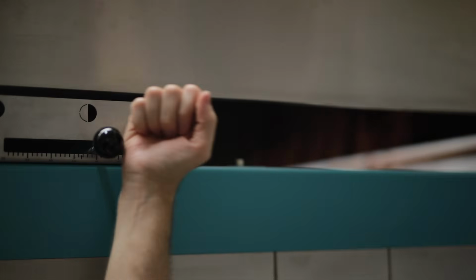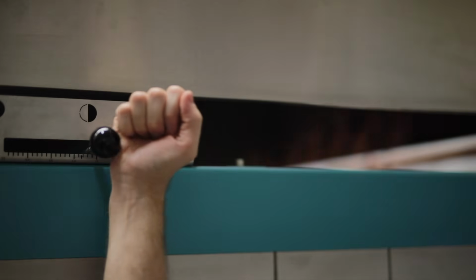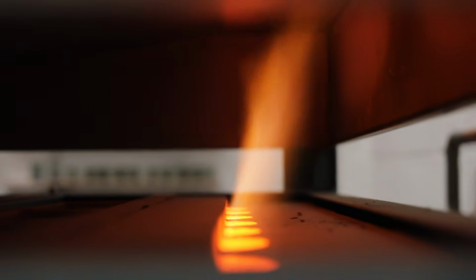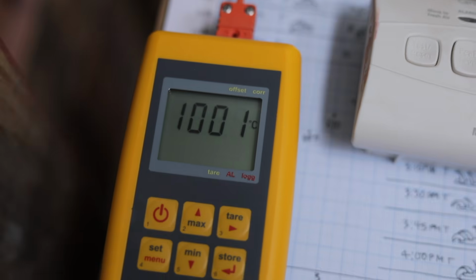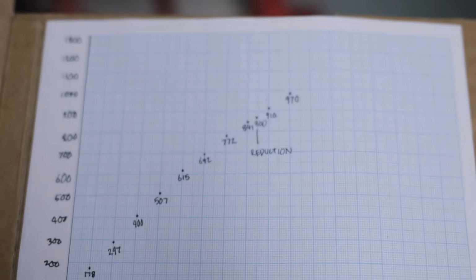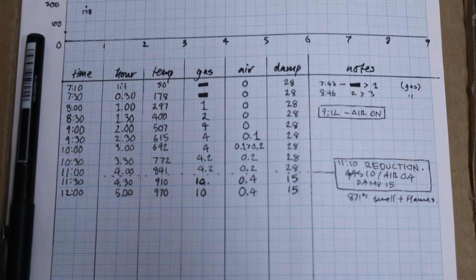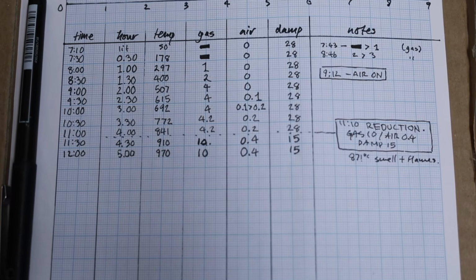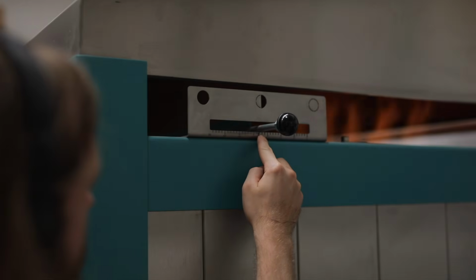To put it simply, we're trying to create an atmosphere that's void of oxygen inside the kiln, as doing so causes the fuel that's burning inside to reach into the clay and glazes themselves and strip away oxygen molecules from iron molecules, which in turn creates the green hues and the scattering of iron flecks that cover pots that are reduction fired, depending on what type of clay you're using, of course.